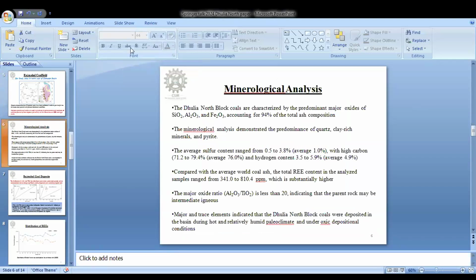If you look at the mineralogical side of it, it was predominantly quartz, as you can understand, is SiO2, clay-rich minerals like montmorillonite, kaolinite, and pyrite, of course, some of the iron sulfide. So there is a certain percentage of sulfur which I have noted. The average sulfur ranged from 0.5 to 3.8%. Some of the depths had very high concentration of sulfur.